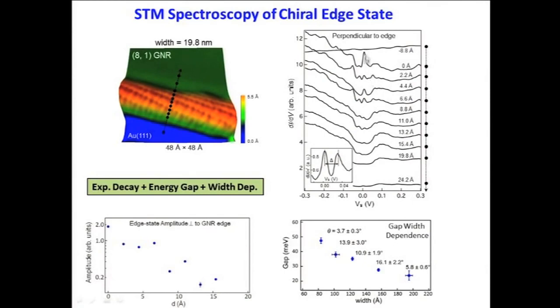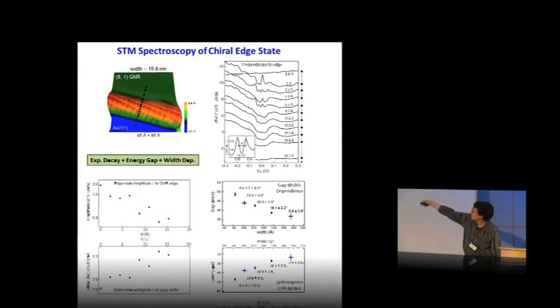Those peaks fall exponentially in amplitude as we move away from the edge. And you can see that here, I've plotted the amplitude of the peaks. Because those peaks fall exponentially, that indicates that they are due to an edge state, because one of the characteristics of an edge state is that its amplitude falls exponentially away from the edge. That's what an edge state is. So here we're seeing an edge state on these nanoribbons, but also another significant fact